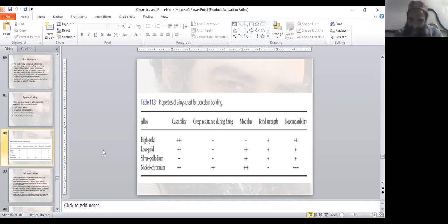Nickel chromium alloys castability much less than high gold content alloys. Creep resistance during firing acceptable, very much acceptable, or excellent you can say. Modulus excellent. Bond strength is poor, that is why usually chipping off is seen there in bridges and crowns. Biocompatibility highly negative.